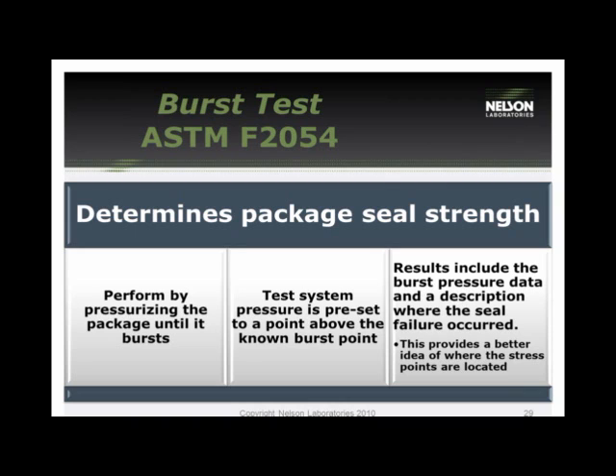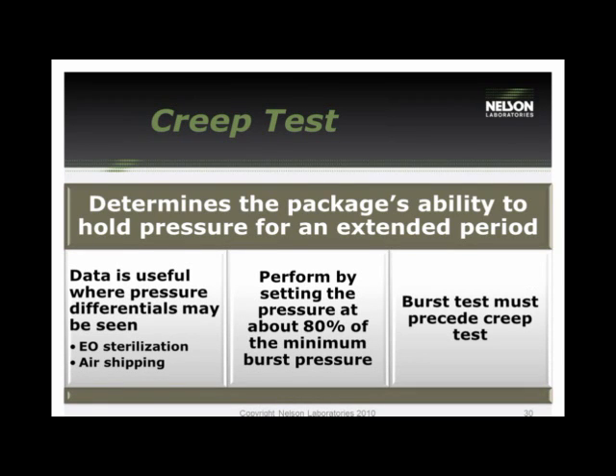The results from this pressure test include a description of where the seal failure occurred and then the actual pressure point that the package popped. This data provides a great idea on where your stress points are located and how they're going to act going through pressure systems. The creep test determines the package's ability to hold pressure over extended periods.